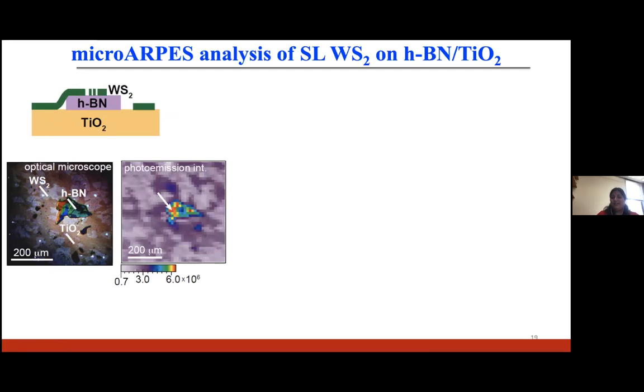There's an enormous amount of information in this photo intensity map. One thing you can clearly see is that this hBN flake, partially covered with a single layer WS2, shows up in this photoemission map. You will also notice a lot of variation in the quality of our sample. Generating these XY maps allows us to find a spot where we have the best quality sample and then carry out all our experiments at that spot.